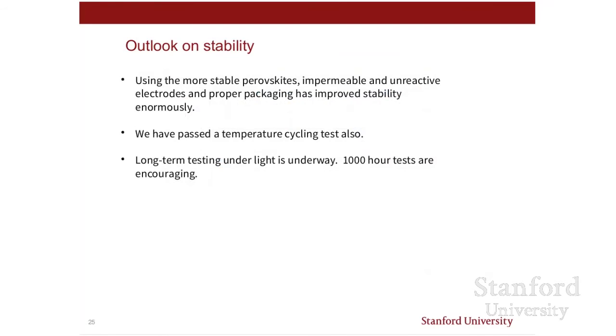So the outlook on stability is that if you use the more stable perovskites, you use impermeable and unreactive electrodes and proper packaging, it looks like at least thermal stability can be obtained. We've also done a temperature cycling torture test where we go back and forth from 80 degrees C into a freezer at -40 to see if the shrinking and expansion will cause it to pop apart. And we passed that the first time. And we're working on long-term tests under light, but those take a bit longer. And at least after 1,000 hours, things look encouraging, but it'll be a while before we'll have longer-term tests.